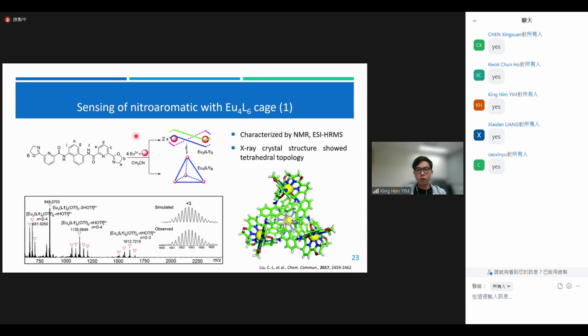And here is one example of using a lanthanide supramolecular complex for detecting nitroaromatics. In 2011, some scientists reported the use of this kind of C2 symmetric ligand with Eu3+ ion to form two different supramolecular complexes. So you see the same ligand, the same metal, but it forms two different supramolecular products. These products were characterized by NMR and ESI-HRMS to confirm the formation and the chemical formula. But the tetrahedron topology can only be characterized by X-ray crystal structure. In this research project, they succeeded in confirming the structure because they got the X-ray crystal.